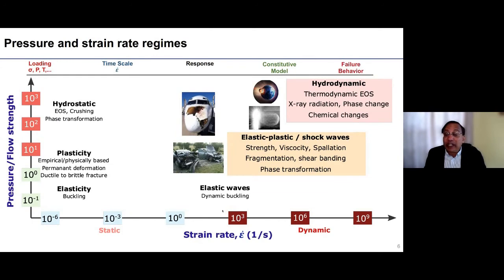So obviously we are looking at a whole range of phenomena, and of course this audience knows very well that we are dealing with dynamic deformation characterized by strain rates, and the strain rates of our interest, the most of our study, is in the range of 10^3 to 10^9. In this range, various phenomena could take place depending on the stress level. Here, the measure of the stress level is given by pressure normalized by the flow strength. And as you approach very high pressures, hundreds of times the flow strength or the yield stress, then interesting phenomena take place.